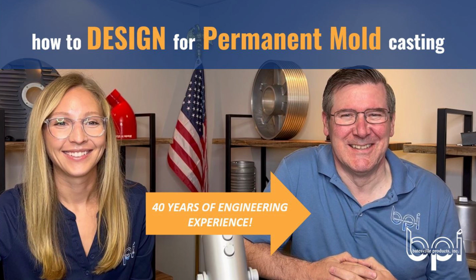What specifically do you need to look for when designing with the core in mind? Well, the core has to be supported somehow. So there has to be a way for us to hold the core on one of the mold sections, typically the bottom. So that's really important, that we can't make a totally enclosed space like a hollow ball type of thing, because there's no way to hold the core in that mold, and there's no way to extract that core after you're done with the casting process.